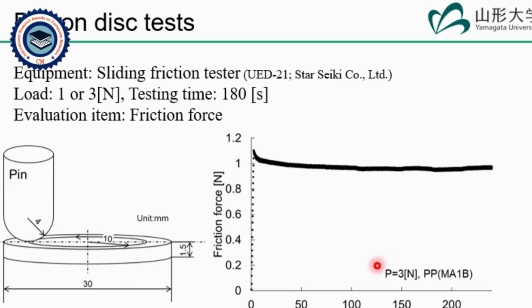The right figure portrays a graph showing the change in friction force obtained from the friction disc test along the time axis. As the figure shows, the friction force increased rapidly at the beginning of the test. Subsequently, it converges to a constant value. This convergence value of friction force, which is defined for this study as the friction force obtained by friction disc, was used as a characteristic value for constructing the model.